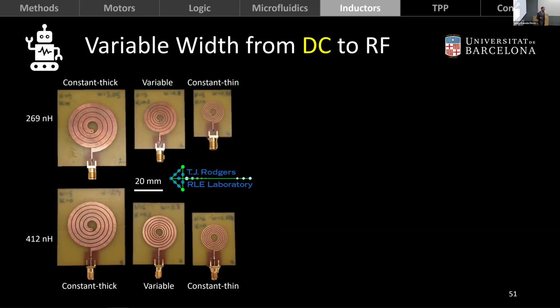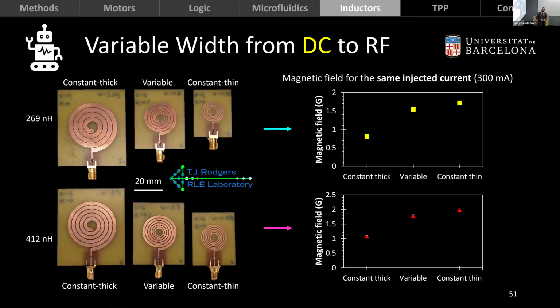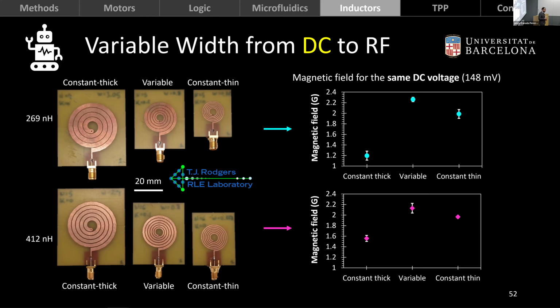And so looking at their performance in DC, we measure the magnetic fields that they generate. And well, if we apply the same injected current, there's no question that the most compact one is going to generate the highest magnetic fields. But it's also going to be the one that heats up the most because of its higher resistance. Now, if we apply the same bias voltage rather than injected current, the resistance comes into play. And we're actually able to see that trade-off. And we found that it is the variable width inductors that are actually the ones that generate the highest magnetic fields. So pretty exciting.